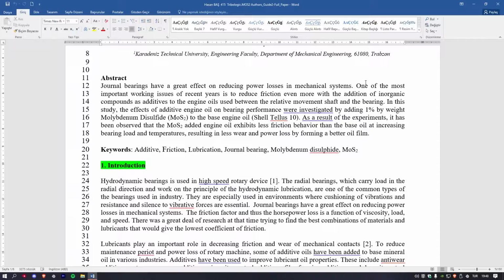As a result of the experiments, it has been observed that the molybdenum disulfide added engine oil exhibits less friction behavior than that of base oil, with increasing bearing load and temperatures, resulting in less wear and power loss by forming a better oil film.